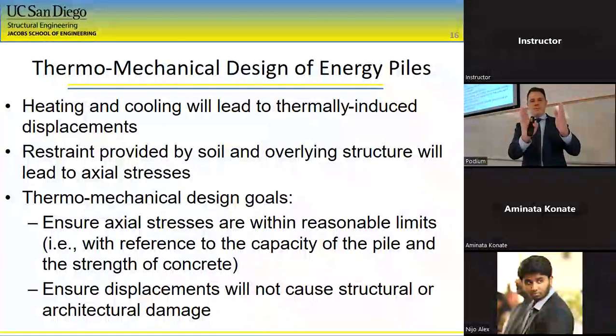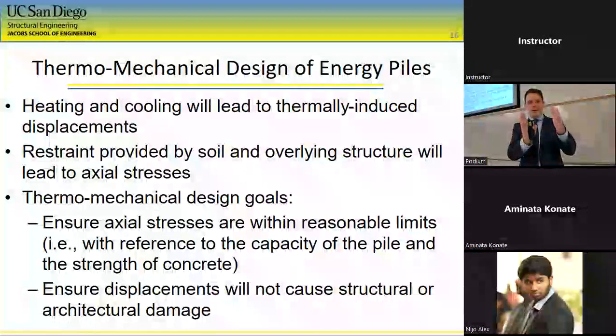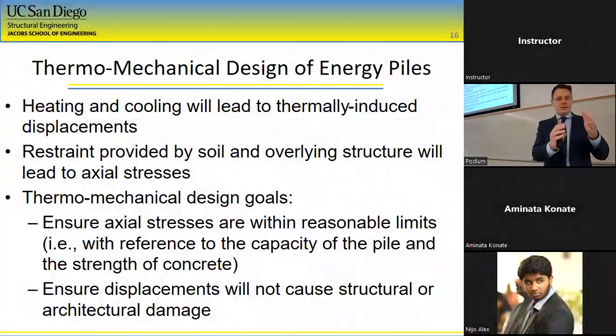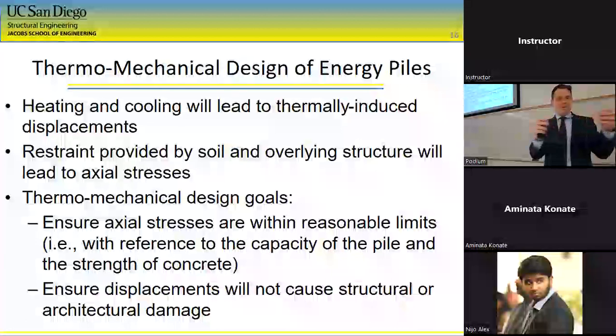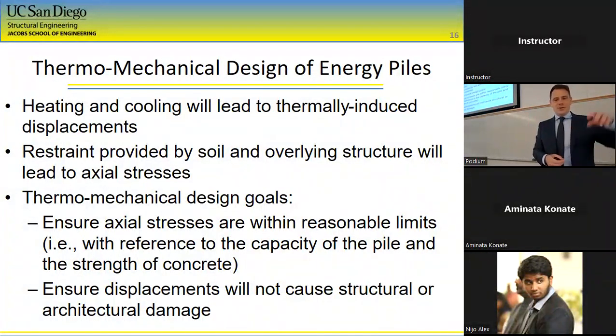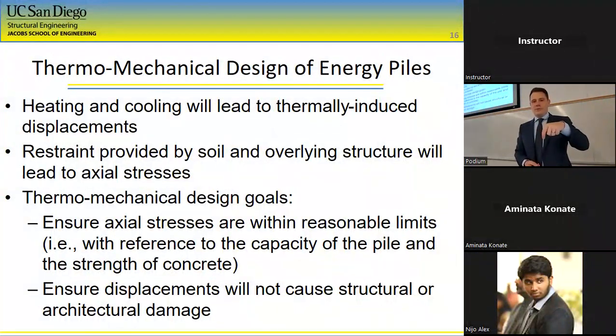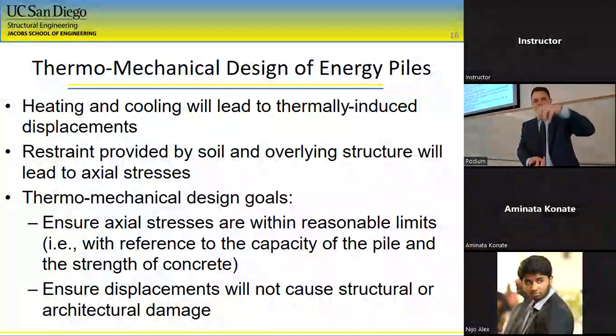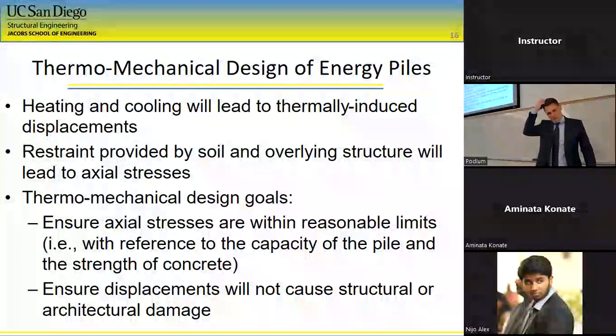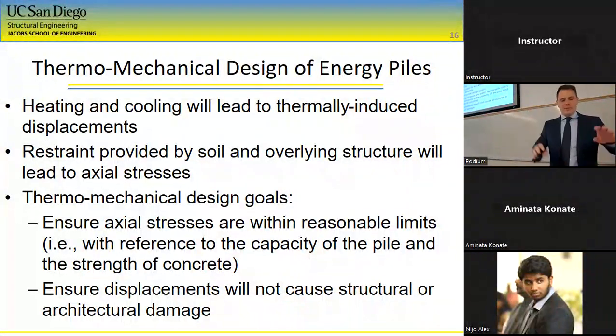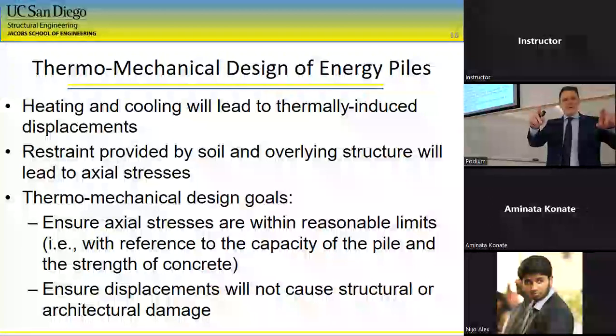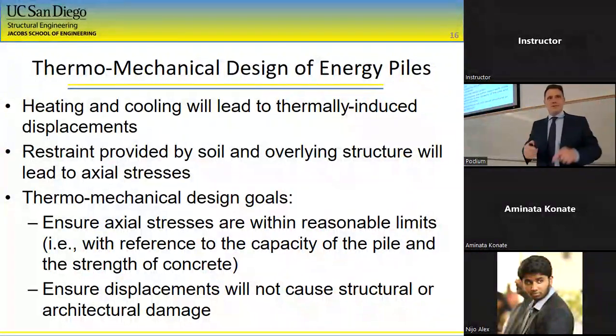If you suddenly prevent it from changing in length, either by friction of the soil around it or by having these end restraints, it's not going to be able to expand. So that energy is going to go into stresses. And you need to be careful because sometimes these piles have very high stresses on them due to the weight of the building above. So suddenly you're having this expansion of the pile and you're also loading it. So you need to make sure that you're within the reasonable limits. And you have to make sure that if there are any displacements at the top, you're not having differential displacements that cause architectural damage.